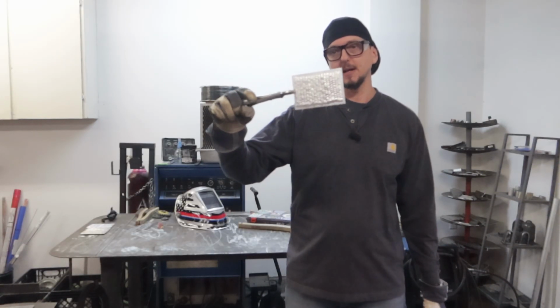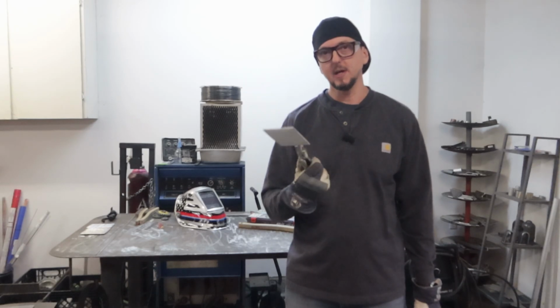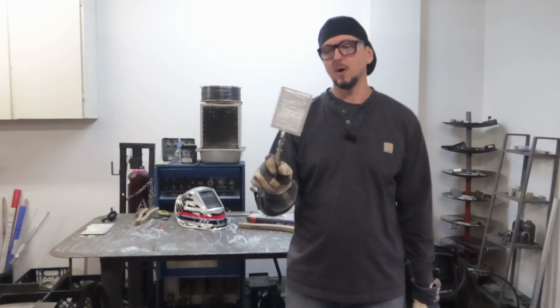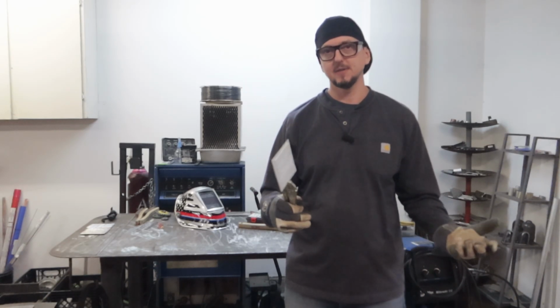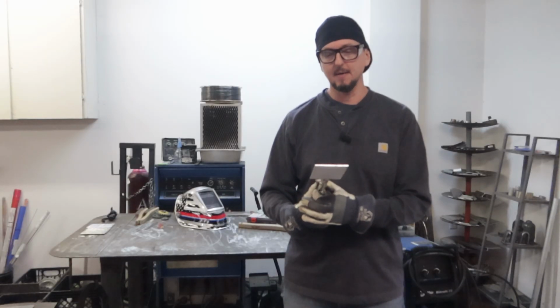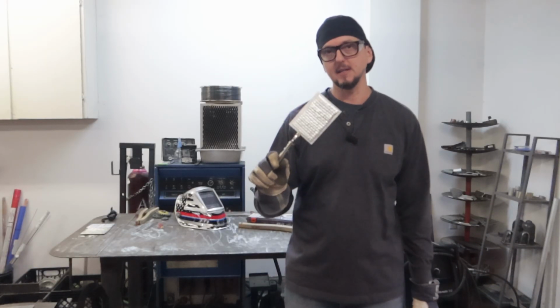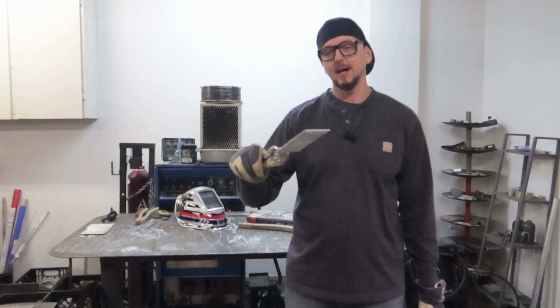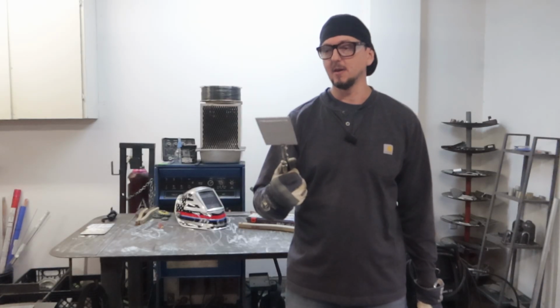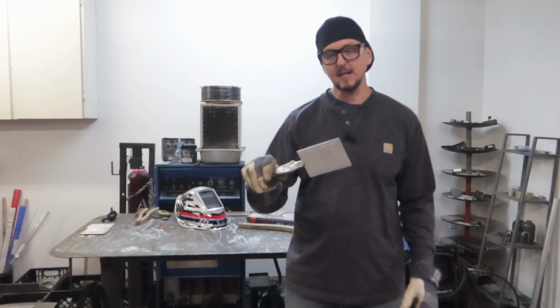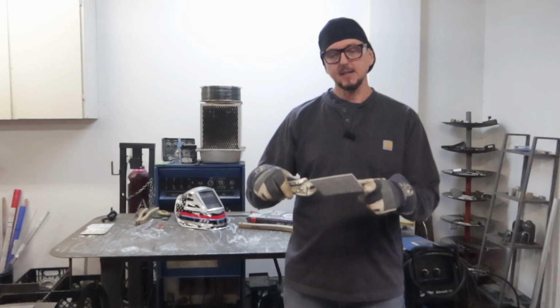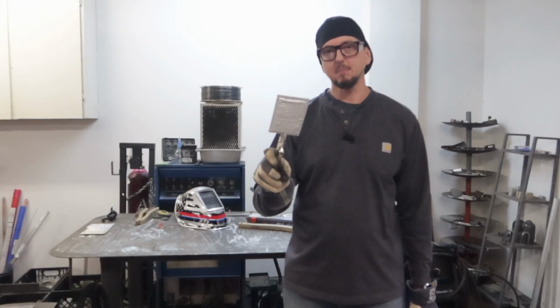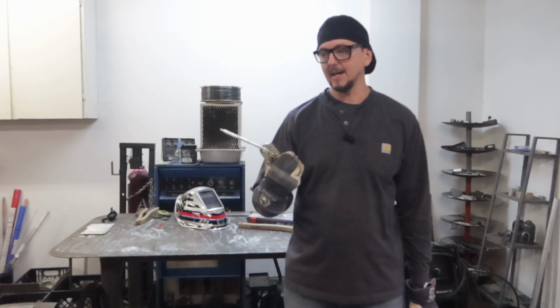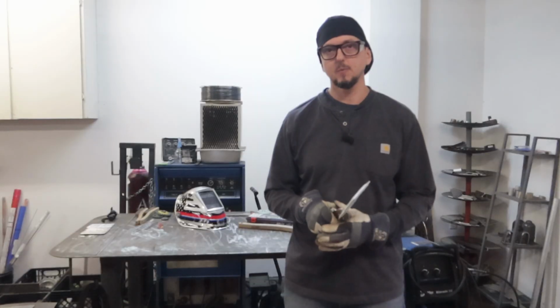I used a combination of 3/32 and 1/8. Honestly, the 1/8 though, by the end, it handles the heat so much better, and I actually prefer the look of the beads with the 1/8 inch filler rod versus the 3/32. So if I were to start over again, I'd use 1/8 inch from the start. Okay, so that's the aluminum surfacing plate, and again, a great project to get started with.